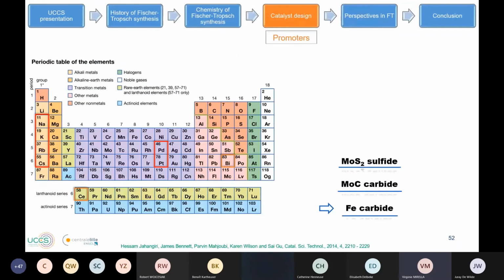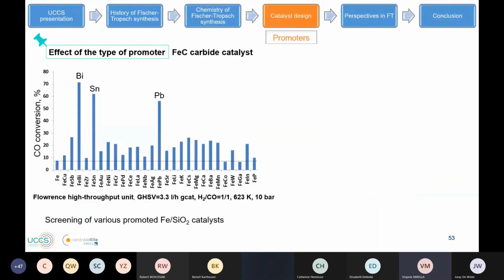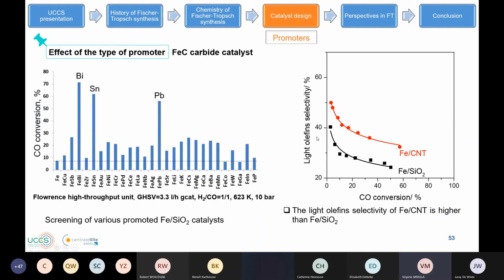Then now I'm going to finish with the carbon nanotube iron carbide catalyst. With the iron carbide catalyst, we study the effect of different kinds of promoters on the RealCat platform. And we have seen that promotion with bismuth, tin and lead increases the CO conversion in comparison to the non-promoted catalyst. Then we observe that the light olefin selectivity decreases when we increase the CO conversion. It's the same that we observe with the molybdenum sulfide and molybdenum carbide catalysts.